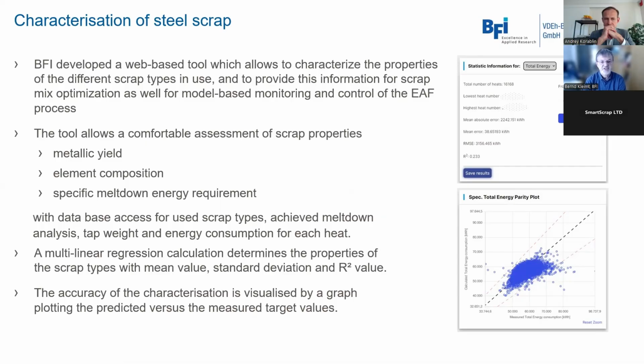With the database access, we can retrieve the data of the used scrap types, the achieved meltdown analysis, the tap weight, and the energy consumption for each produced heat. And out of these data, we can apply a multilinear regression calculation, which determines the properties of the scrap types with mean value, but also with standard deviation and R² value to have an indication on the reliability of the statistical determination of the scrap properties.